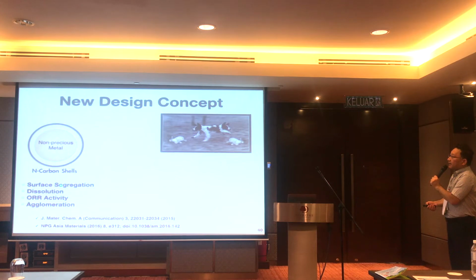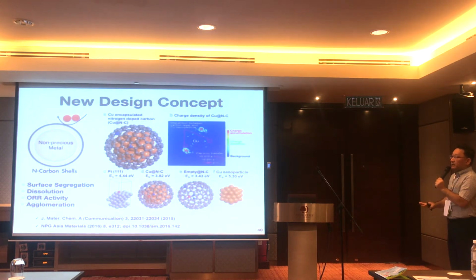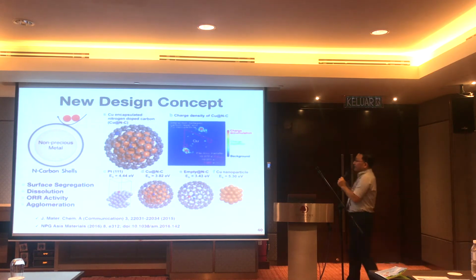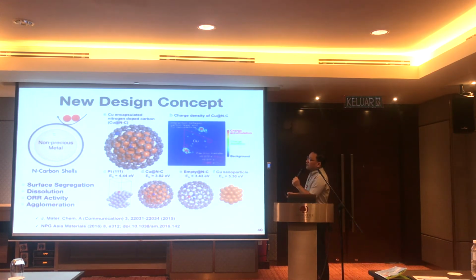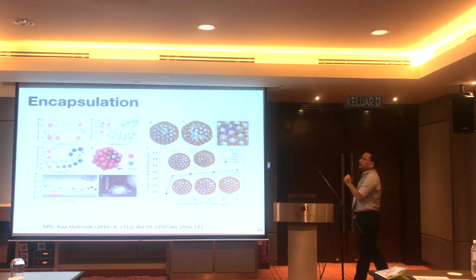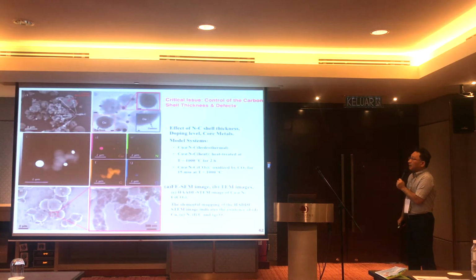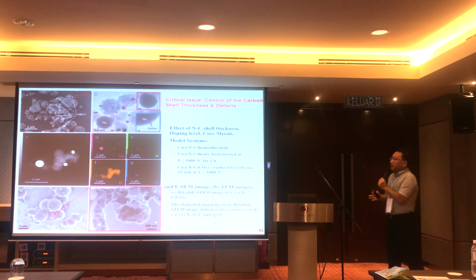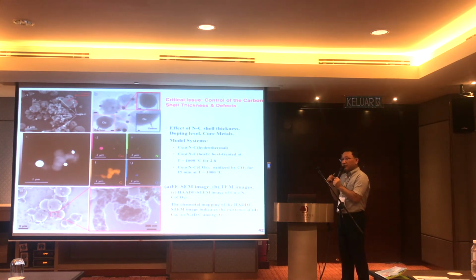As I told you, there's a very strong surface segregation of core metal to the surface, right? Then dissolution issues. How can we block surface segregation and dissolution problems? I propose that you can encapsulate the catalyst material by using carbon shells. Then these carbon shells regulate the oxygen adsorption and also block the dissolution of core metals. Right? It's working. We call it encapsulation, and experimentally they designed it. Here, copper core metal, and they encapsulate copper with a very thin layer of nitrogen doped carbon shell. Computationally, you need less than 1 nanometer thickness. 1 nanometer thickness is almost impossible, right? So how to control the thickness?